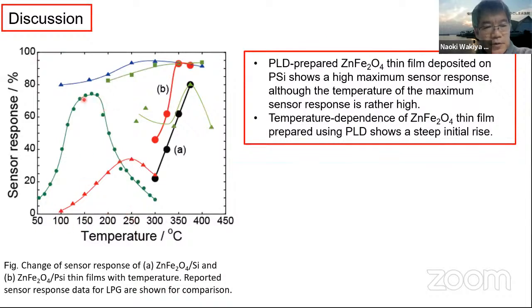So this slide shows the reported value, and our data is here, on porous silicon and on silicon. This result shows that the PLD prepared zinc ferrite thin film deposited on porous silicon shows a high maximum sensor response, although the temperature of the maximum sensor response is rather high. But we'd like to say that this steep slope shows that this thin film has a high selectivity for the LPG at these temperatures.